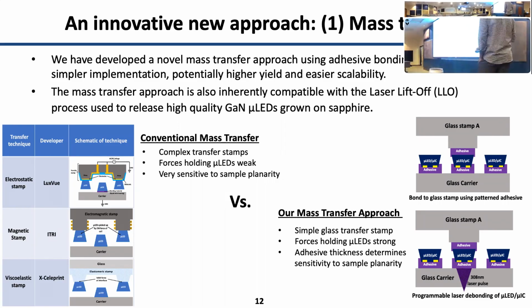However, in our approach, which is shown on the right side, we essentially use adhesive bonding and laser debonding in order to do the mass transfer. So here what we do is we use a lithographically patterned glass stamp with a coated adhesive, which we bond to the device we want to pick up. And then we use a laser debonding to release the device and transfer it to the stamp. And finally, we can do a laser debond step to release it from the stamp to a target.